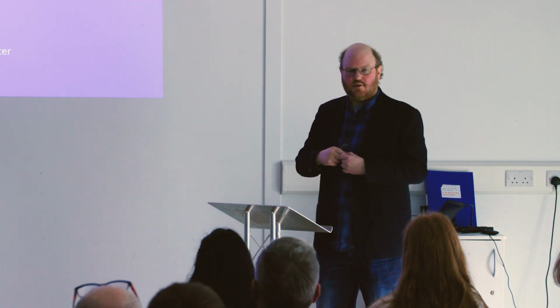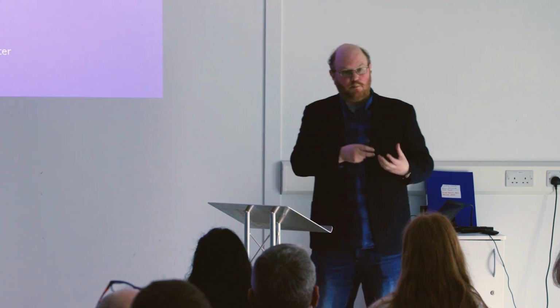So we have several projects on that right now, understanding if we take these nanocomposites and put them through traditional mechanical recycling, what happens to the dispersion? Does the presence of that nanofiller actually compensate for any degradation to the polymer matrix? So if the molecular weight of the polymer is reducing with each cycle, does the presence of the graphene actually counteract that? It means the polymer can be recycled for more cycles without needing to add additional virgin material to compensate for that. And so far, all of the evidence seems to suggest exactly that: the nanofillers get dispersed better each time it cycles. Each time it gets chopped up and made into a new component, its performance is getting better because you're dispersing it better. So far, it seems to be very highly recyclable, which is nice to know.